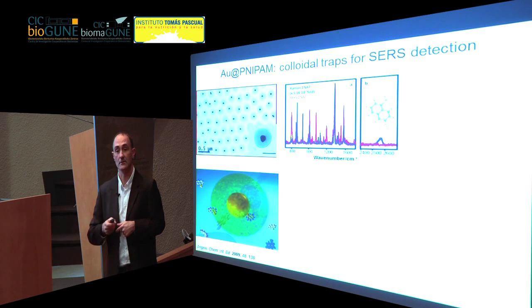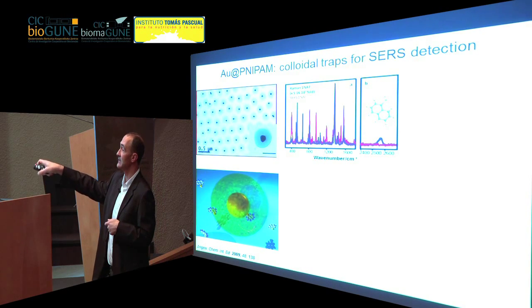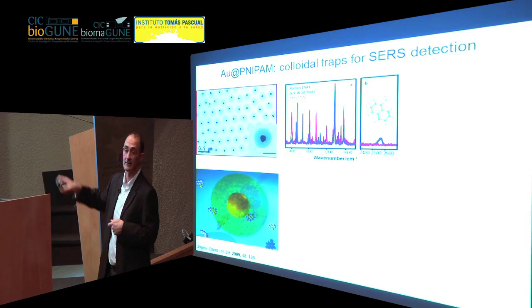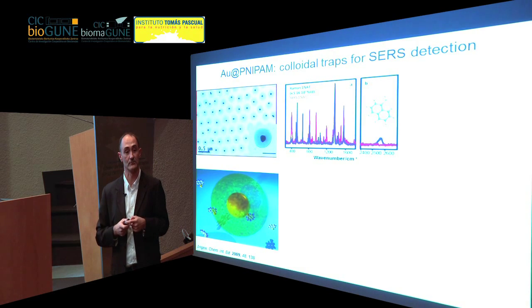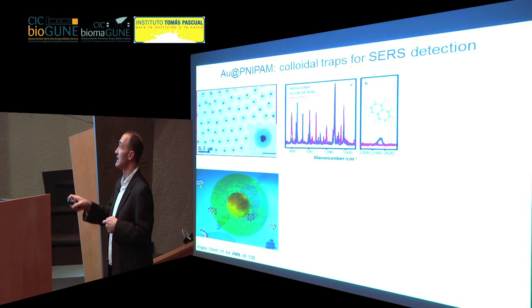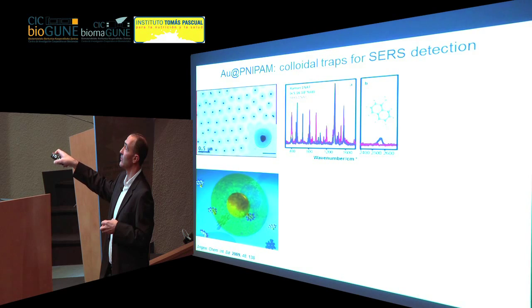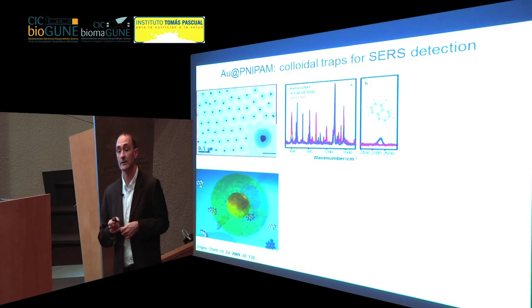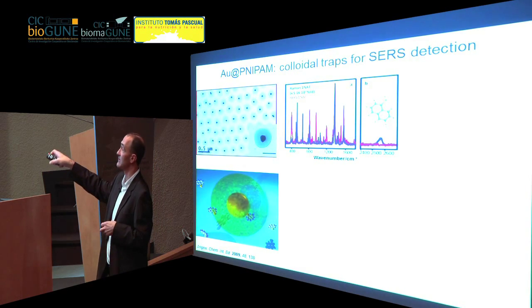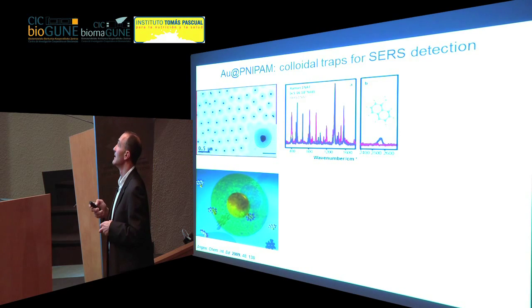Okay, so now we go and design the system in such a way that we let certain molecules diffuse through the pores of the shell and then bind to the gold core, and then we can measure the surface enhanced Raman scattering spectrum of these molecules. And this was the easy example where the molecule has a thiol group. So if it can diffuse through the pores of the microgel, it will bind chemically to the gold, and then you can easily get the Raman spectra. So this is what you see here.